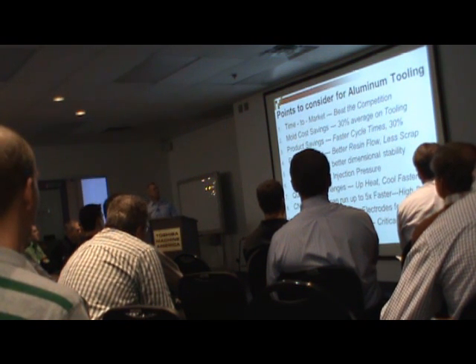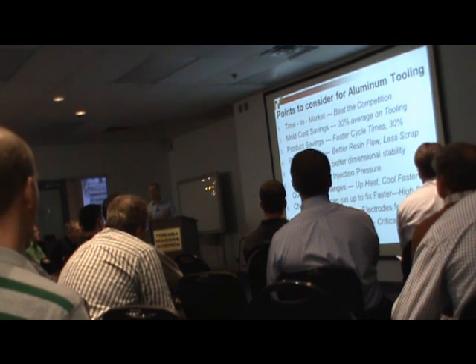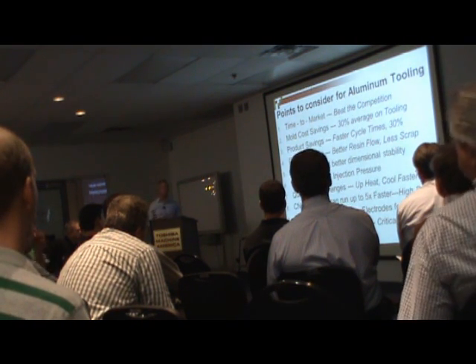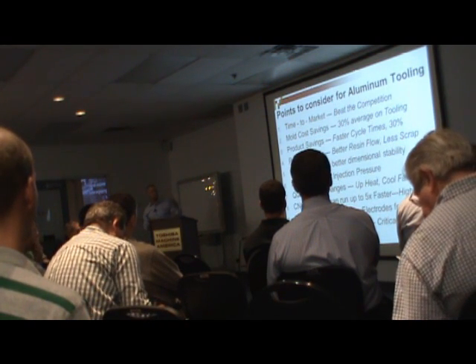Minimal warp and better dimensional stability. In some cases, lower clamp and injection pressure, again, depending on the material, depending on the part geometry. Quicker mold changes we discussed. Your CNC machines run up to 5 times faster, we've seen. Less wear on cutters, fewer electrodes. You can hard anodize or nickel plate for critical areas.